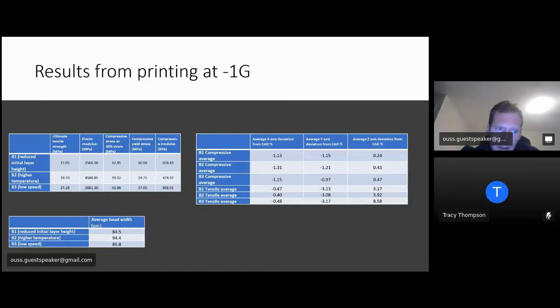I tested at reduced layer heights, higher temperatures, and lower speeds to see if I could get a good adhesion onto the bed. Once it's stuck onto the extrusion bed, which is the plate that you 3D print items on, once it was stuck firmly on there, I had no problems at all. So I then played around with reducing the layer height, that's the distance between the extrusion head and the plate, and printing at a higher temperature, because as you know, if you print at a higher temperature, your viscosity goes down. And I tried printing at a lower speed just to get slightly more adhesion from the extruded material.